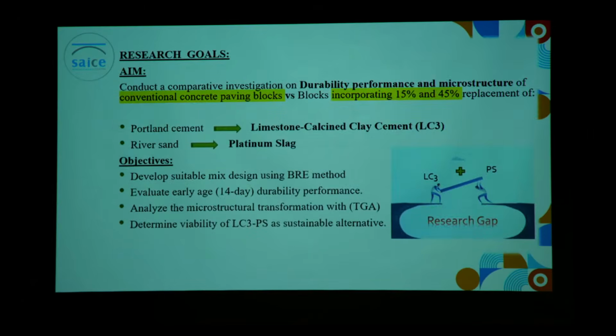The goal of the research was to conduct a comparative investigation of the durability performance and microstructure of the conventional paving block versus blocks incorporating our replacement materials at 15% and 45% levels. The Portland cement is replaced with LC3, and the river sand is replaced with the platinum slag waste. The objectives were to develop our design mix using the BRE method, evaluate the concrete in 14-day early age testing, validate our results using microstructure and TGA analysis, and determine whether replacing the normal materials in the concrete mixture would be viable.